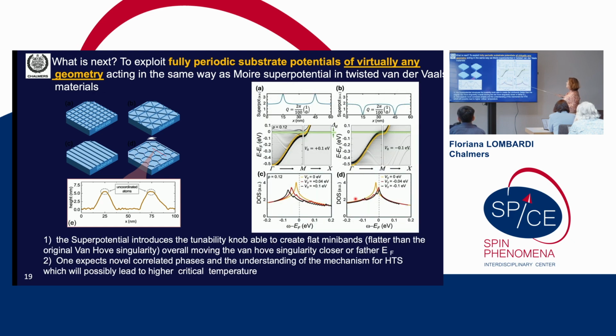And what is happening here, our colleagues made some preliminary investigation. And what you have is that because of this Moiré superpotential, depending on the sign of the substrate voltage that you are imposing, you can split your band into several mini bands. And these mini bands, if for instance the potential is positive, become even flatter. So you can tune your Van Hove singularity closer or farther from the Fermi energy by imposing on the film any kind of symmetry that you want. But this is work in progress.